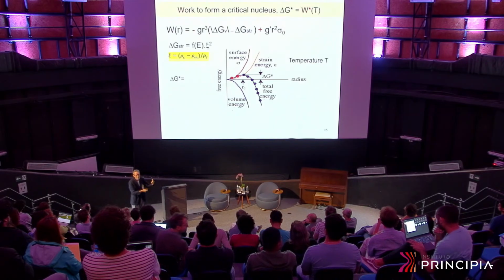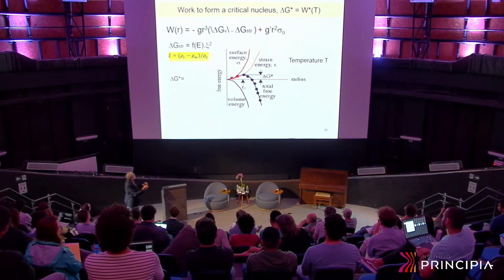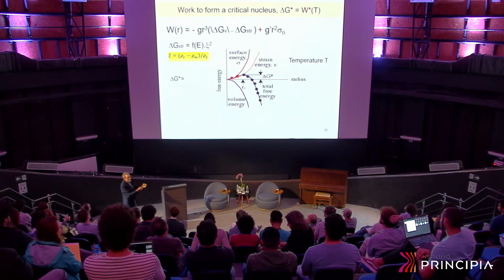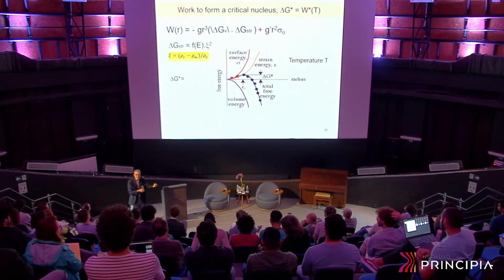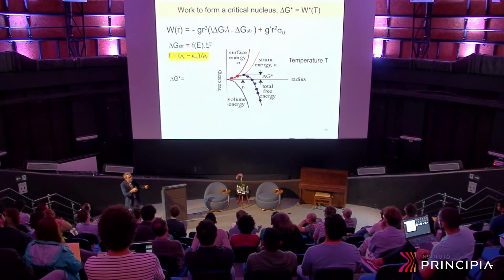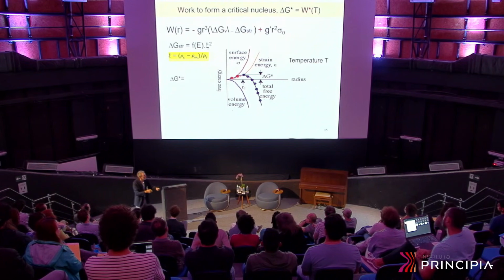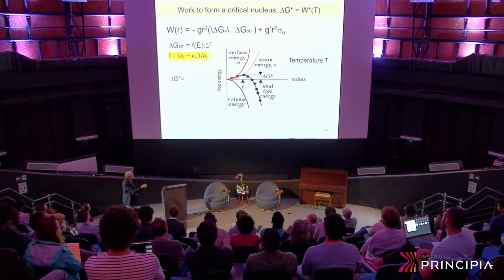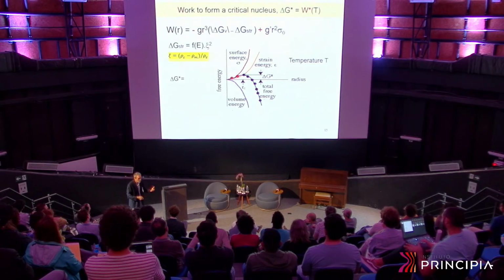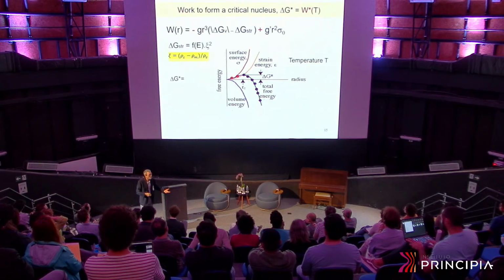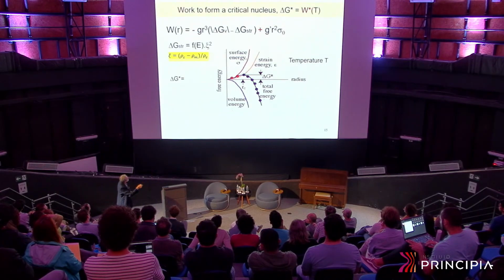positive interfacial energy. You also have strain energy, because the density of the crystal is different from the density of the liquid, so you have some local deformation. They're both positive, but the volume free energy is negative because the crystals always have lower energy than the liquid. So overall, the interesting curve is this curve here.